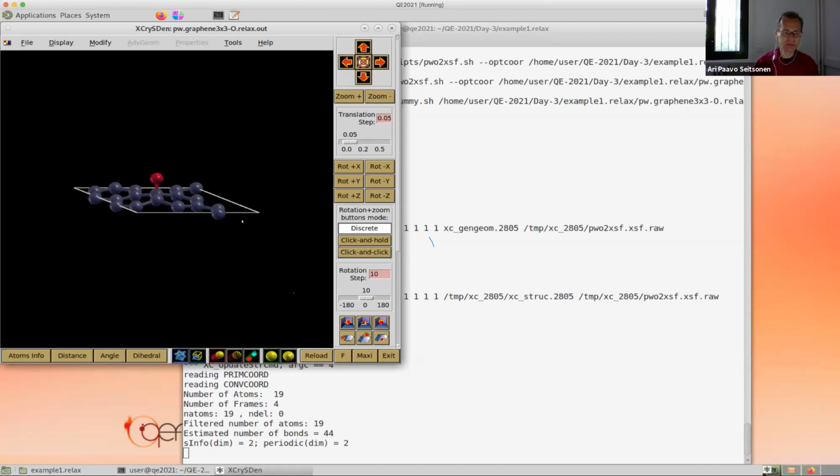But today in this example, indeed there's a dipole. I mentioned that this oxygen gets polarized and so on. So in really good calculations, one would indeed put the dipole correction so that it's in between the two layers, so that this discontinuity or step in the potential which is added in the dipole field would not affect directly the electron structure of this structure.